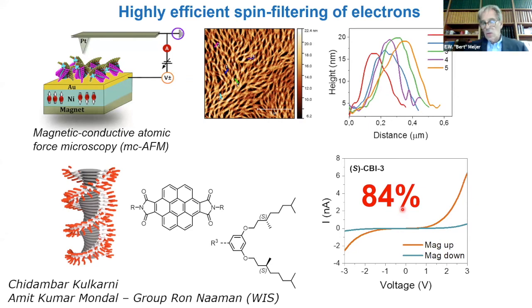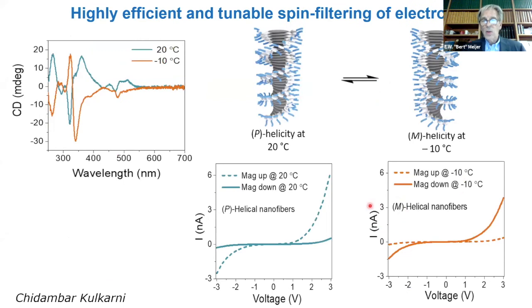Now you could argue, do you do that right? And therefore, this molecule has the beauty that if you assemble it at minus 10, it gives you the opposite chirality. So the same molecule, assembled at 20 degrees, gives you the P helix. If you do it at minus 10, it gives the M helix. It's diastereomeric, so the CDs are not mirror images. But if you now do the IV curves, I hope you can appreciate that if you take the P helix, the big one is magnetic field up. And if we do it for the M helix, it is the magnetic field down that is the highest. So with the same molecule, but different chirality, you get this type of structure.